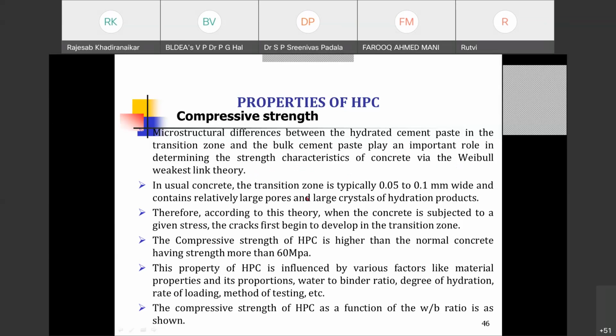So in usual concrete, the transition zone is typically 0.05 to 0.1 mm wide. Now it reduces in this case, and it has relatively large pores and large crystals of hydration products, that are CH crystals. So porosity is also higher, but now it reduces in this case. Therefore, according to this theory, when the concrete is subjected to a given stress, the cracks first begin to develop in the transition zone, but now the transition zone is strengthened. The compressive strength of HPC is higher than normal concrete, with a minimum of 60 MPa.